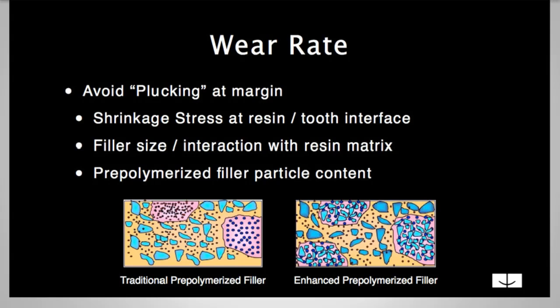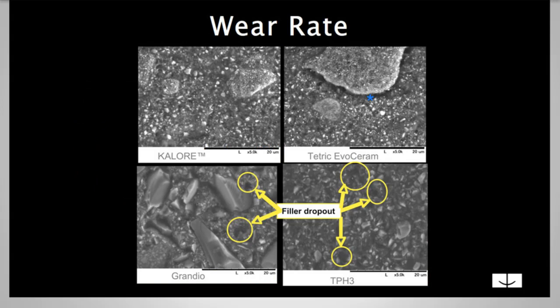So what Kalore has tried to do is change some of those things, and what they did is that they had an enhanced pre-polymerized filler. So they had these fillers that are already cured essentially, creating a heavier weight in there, and that has special lining that can bond better with the resin matrix, hence decreasing the plucking at the margin. So here's just an example of some scanning electron microscope images that show what plucking looks like in different materials. But Kalore has definitely decreased that plucking rate.